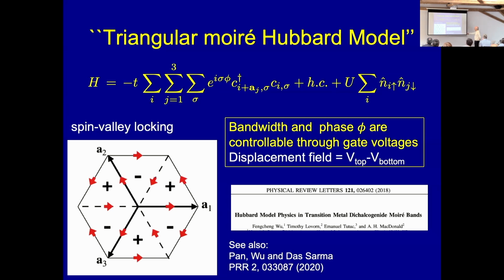So we have, again, two species of electrons with, if you want, a pseudospin living on a triangular lattice. This pseudospin is actually not quite the physical spin. It's the result of the spin valley locking due to the strong spin orbit in the system. But for all practical purposes, we can just think of it as a spin degree of freedom. And the electrons hop on the triangular lattice. But now what's really interesting is that you see here, the hopping acquires a phase, which is spin dependent. And the pattern of the phase has been mapped here, the arrow indicating positive phase, according to this pattern here. So this is the Hamiltonian. And many of the parameters of this Hamiltonian are controllable by these gating techniques.